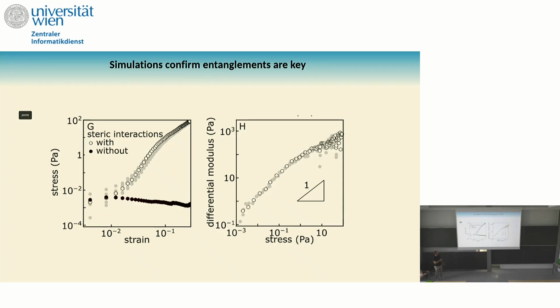And if the contacts matter, then you would see a huge difference between both. So these are the two curves. This is stress as a function of the strain. This is with the steric interaction. But now if you turn off the contact interaction, you see that the stress doesn't change much, which means that if I translate that in terms of modulus, which is the derivative, then if I have repulsive interaction, I have a clear increase, strain stiffening. But if I don't have steric interaction, the modulus would be just at 0. This is a proof, which you can't do experimentally, that comes from simulation. It tells you that really the contacts that form are very important, and you can show it numerically.